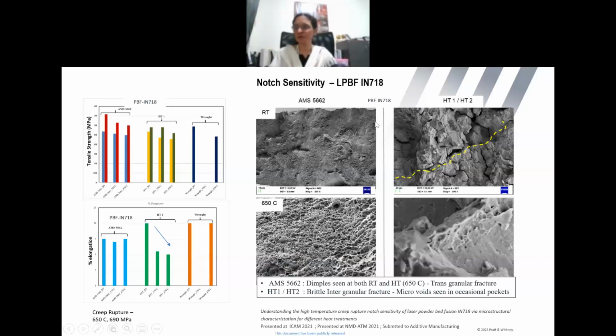Inconel 718 is a workhorse alloy in the cast and the wrought form. It's been used in the aero engines up to temperatures of 650 degrees, at least for the last 50 to 60 years. And it is one of the most well-studied alloys, along with 625, in the additive manufacturing community, by electron beam melting, laser powder bed fusion, direct energy deposition, wire arc additive manufacturing, everything put together in the last 10, 12 years.